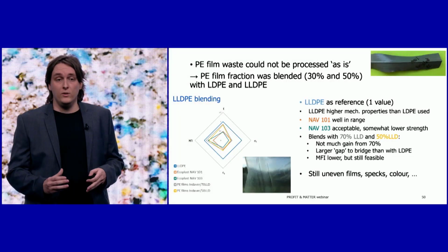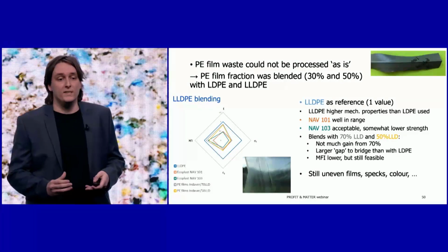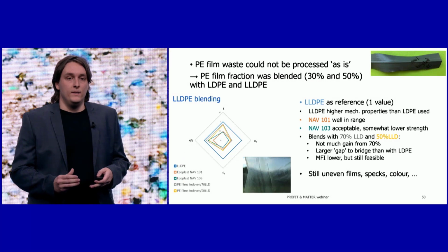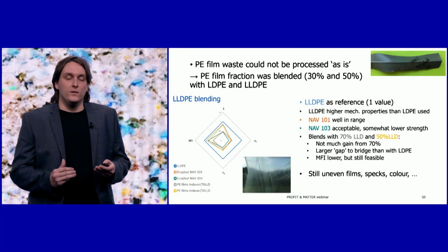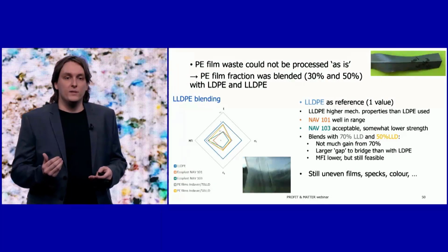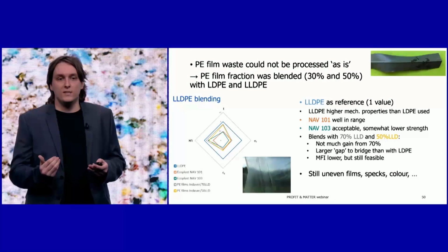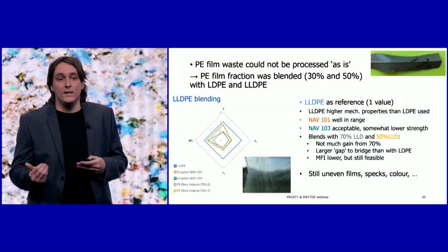If we then look at the 50 and 70% LLDPE blends, then we see because the LLDPE has higher properties, the gap to be bridged by the PE recyclate is more difficult.